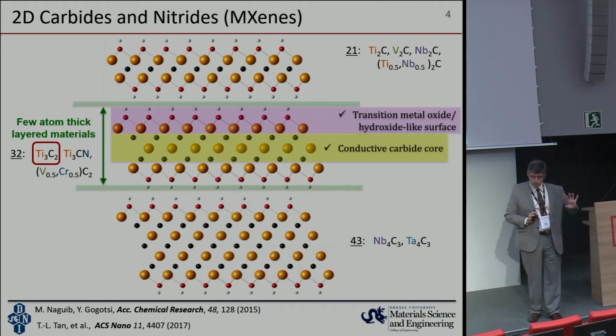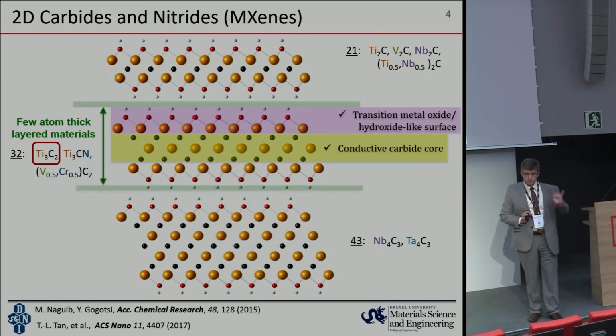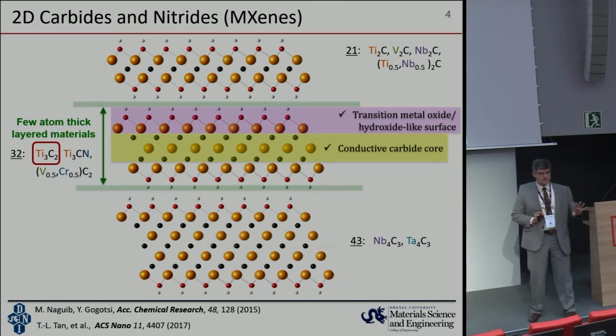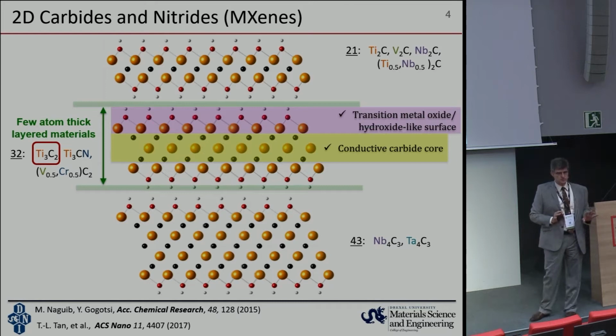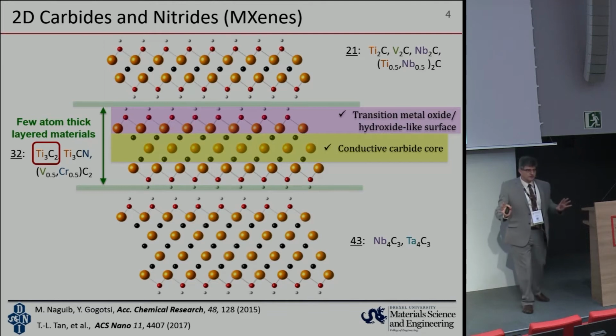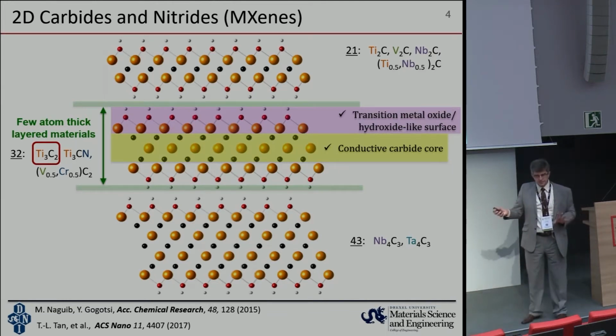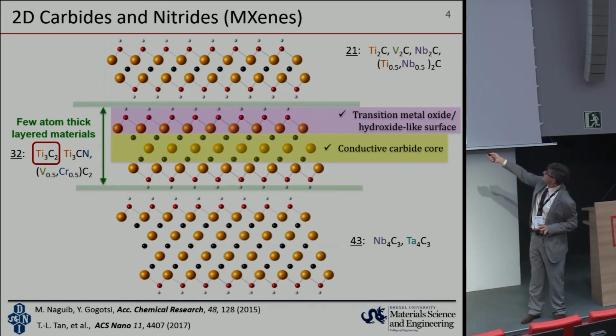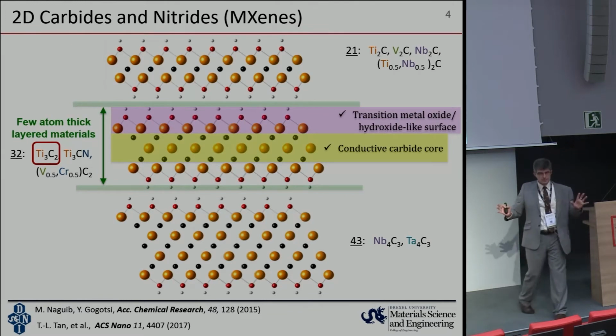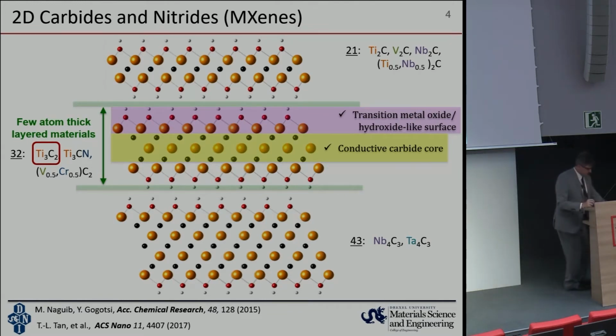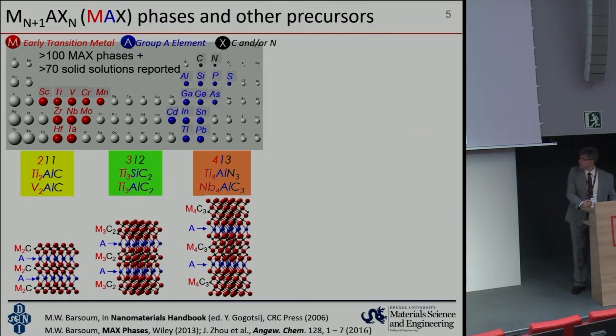About 30 have already been experimentally reported and synthesized, but several dozens are possible as simple compounds, and potentially millions if you consider solid solutions can be created here. So it's a very large, quickly growing family of materials. I'm not going to talk about semiconducting properties, but for example, for this thinner structure, surface termination can pull electron density, opening the band gap, so semiconducting materials are possible. But for the application I'm going to talk about, we care first of all about metallic conductivity and redox here. So how do we make them?